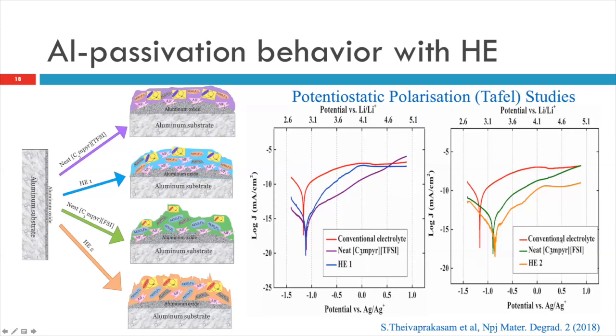So what we have done here is use a conventional electrolyte and an ionic liquid in a hybrid mode. At least 39% ionic liquid is used, and that's an optimum concentration I've seen. And we have seen that it's creating a very good surface film and enhancing the cycle life of LCO. Also, you can extend your potential range up to 4.4. And we looked at two different ionic liquids, with TFSI and FSI anions. The anion effect was also looked at. So we have seen that TFSI is better for some applications.